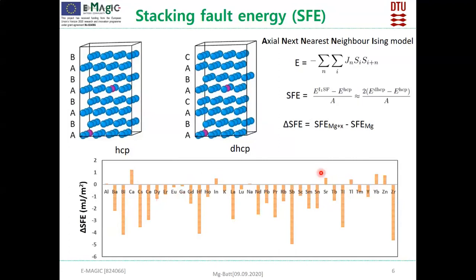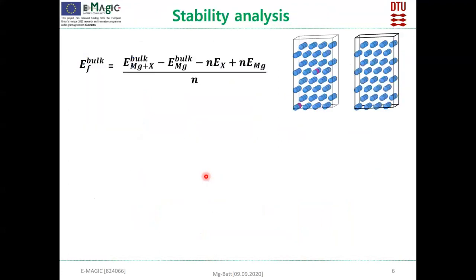So normally these 33 elements we studied are known to make magnesium ductile, but we expect this discrepancy may come from the low doping concentration we used in the study. So the doping concentration we used is 2.98 at% of dopant in our studies. So we think this discrepancy may come from the doping concentration.